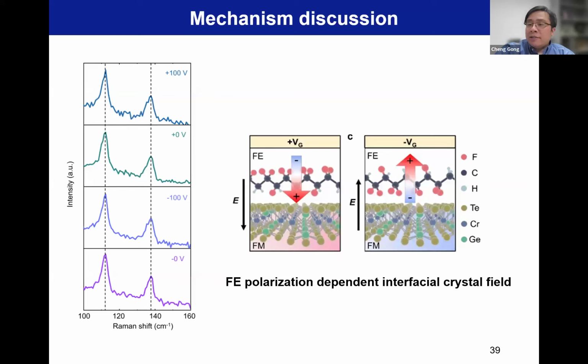But here is a layered system. The strain is hardly transferred to different layers. So as you can see, in this Raman spectrum of this heterostructure under different voltages, at least within the detection limit, we did not see observable strain in the 2D magnet. And doping is also not a main mechanism here.